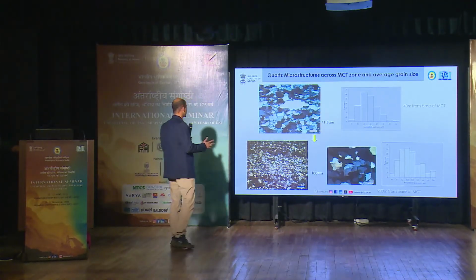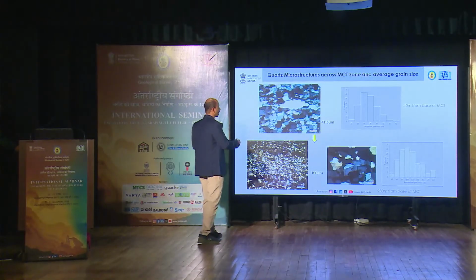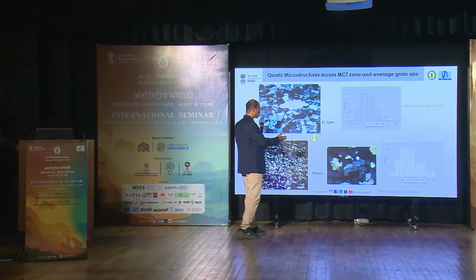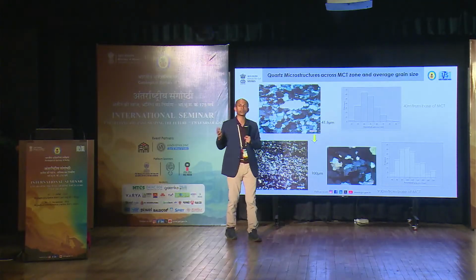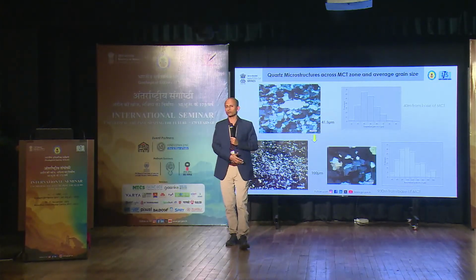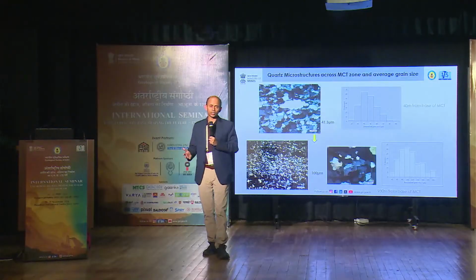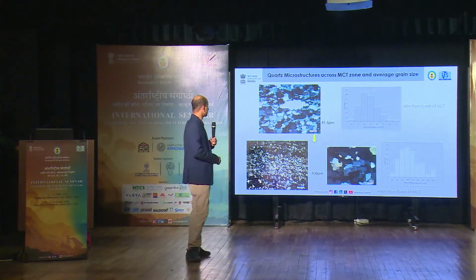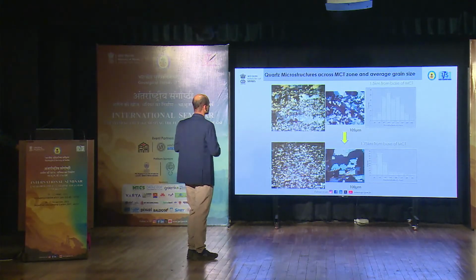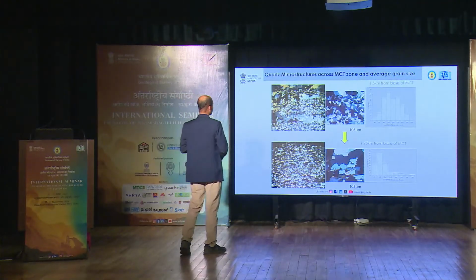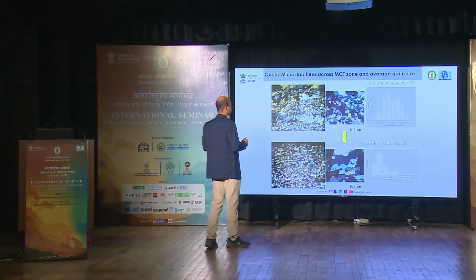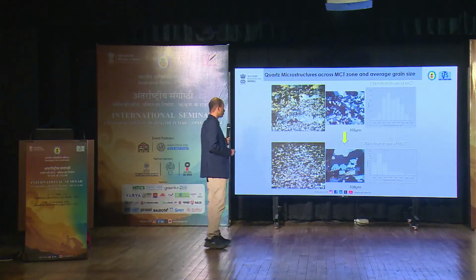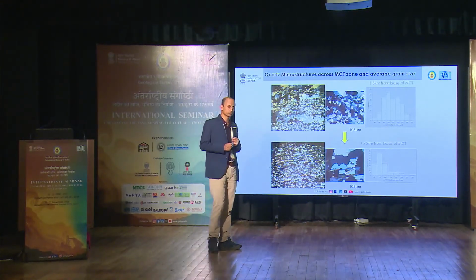We see wide scale development of ribbons, development of pinning structures, window structures, evidences of grain boundary migration. That means we have shifted from subgrain rotation to grain boundary migration within 1 kilometer distance. Next. Further going across, the next sample at 1.5 kilometer, the grain size has increased to 105 micron, and at 1.75 it has further increased to 108 micron.